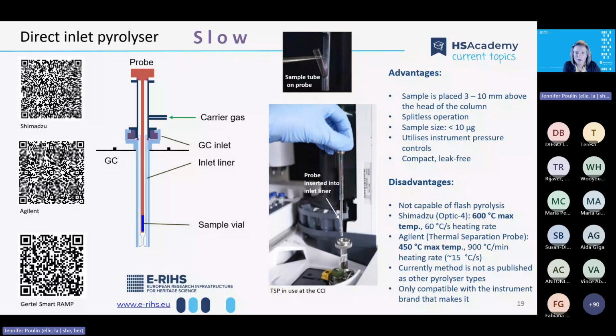Well, pyrolyzers that can only perform slow pyrolysis rely on the heating rates of the GC inlet, and these can be referred to as direct inlet types. The sample is inserted into the GC a few millimeters above the head of the column, and then the inlet is heated rapidly, but not instantaneously, to a pyrolysis temperature. This is the pyrolysis method that I now use at the CCI, and I know that it's also used at the Getty, the Art Institute of Chicago, and the National Gallery in London.